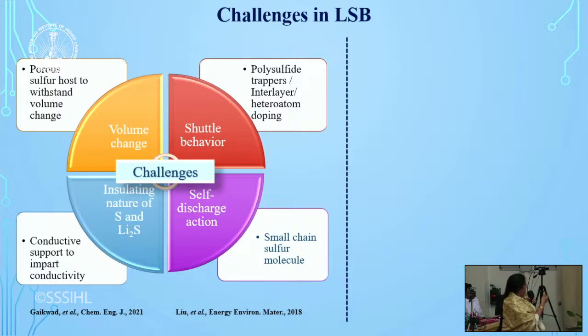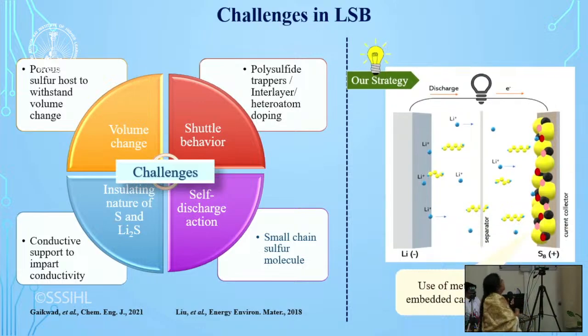So this shows how to address all the challenges. You can see over here, the porous sulfur host withstands volume change. So we need to have a porous, sulfur is an insulator, isn't it? So this sulfur as it is, if you use, it doesn't work as a cathode. So you need a conducting medium. So we have used highly porous carbon host for sulfur, and this solves the problem to an extent, but not to that much extent. Then how to arrest this shuttle behavior?